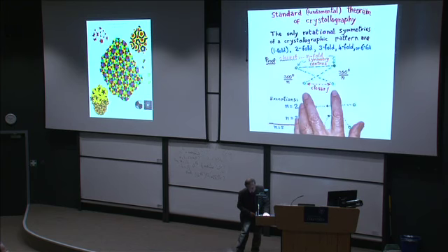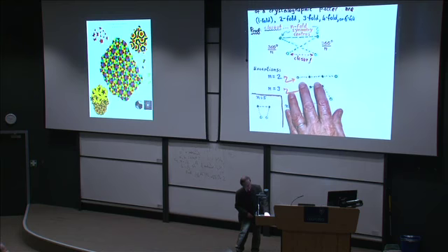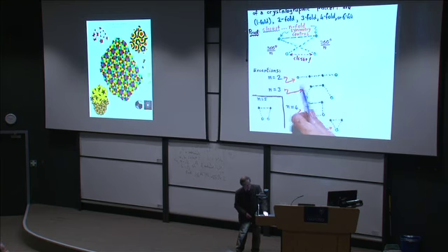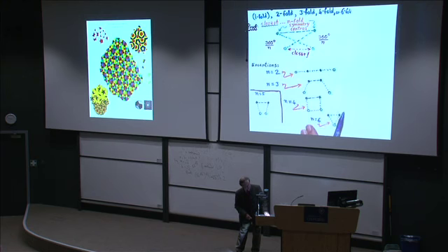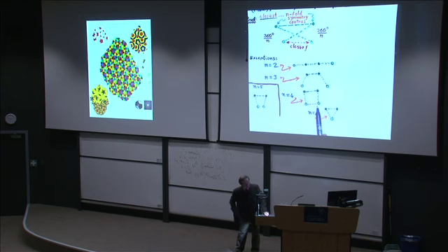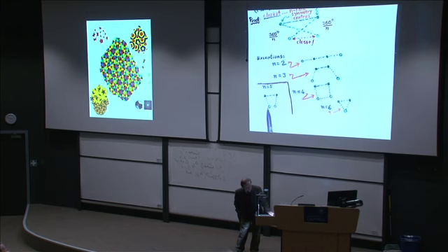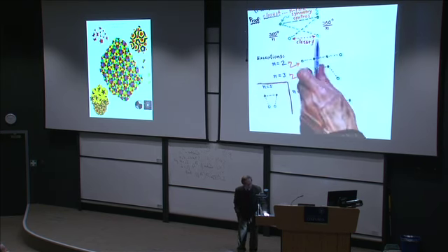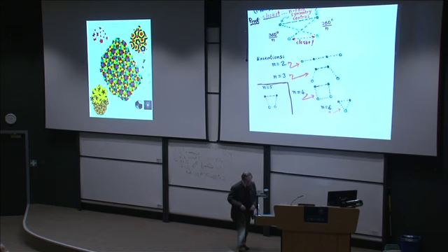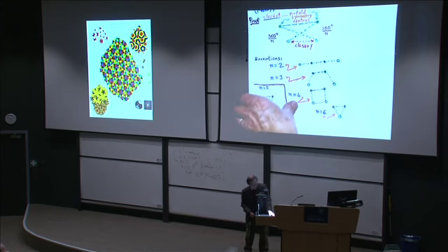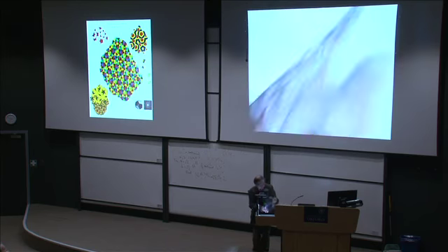The only exceptions are where they're not closer together. If n equals 2, they're not. N equals 3, they're not either. N equals 4, they're exactly the same distance. N equals 6, you get away with it because they coincide. So those are the only possibilities. If n equals 5, you can see they're obviously closer here. If n were larger than 6, they'd cross over, but they'd still be closer together. It'd be more like that picture. Okay, so that's the proof. Really very simple. You can understand that pretty reasonably, I hope.